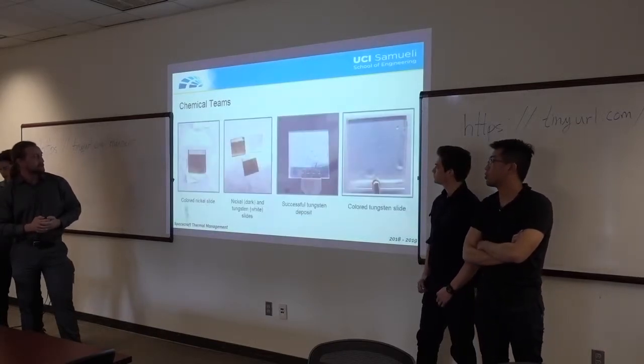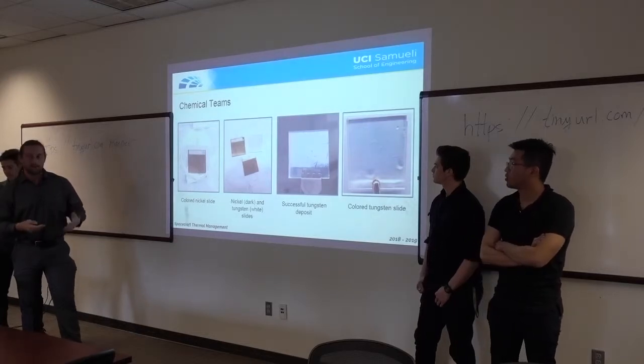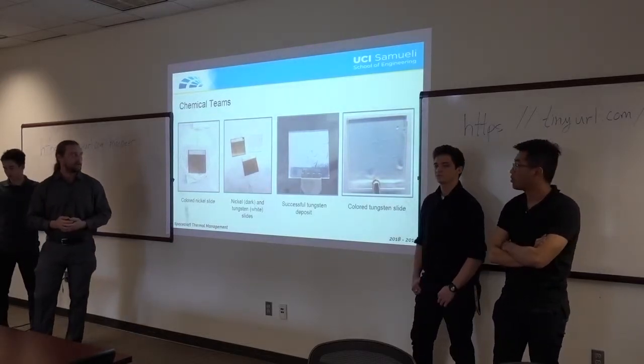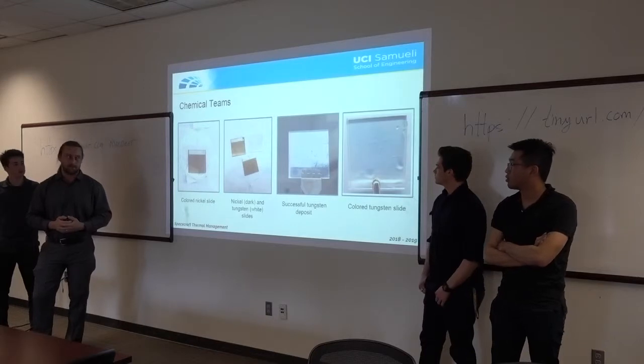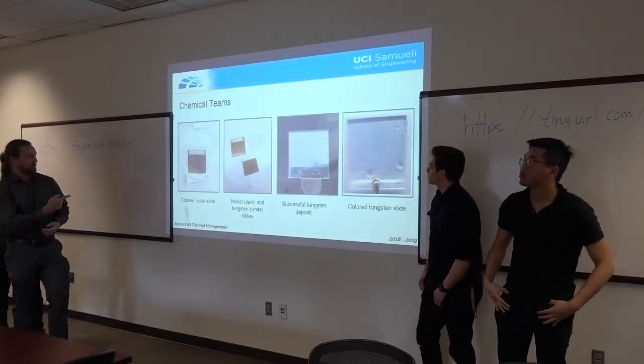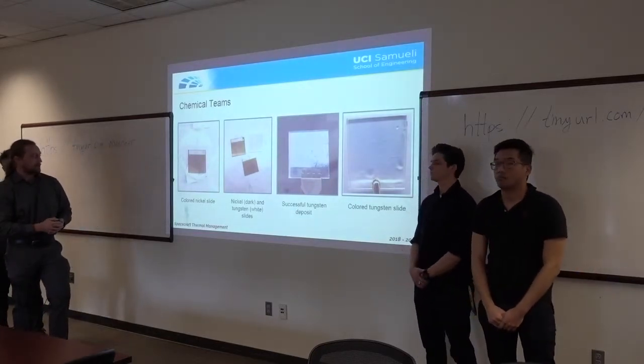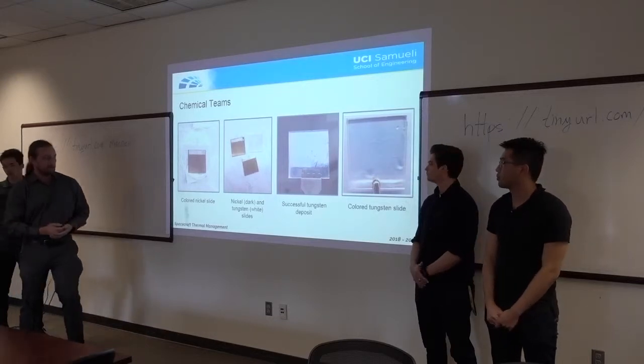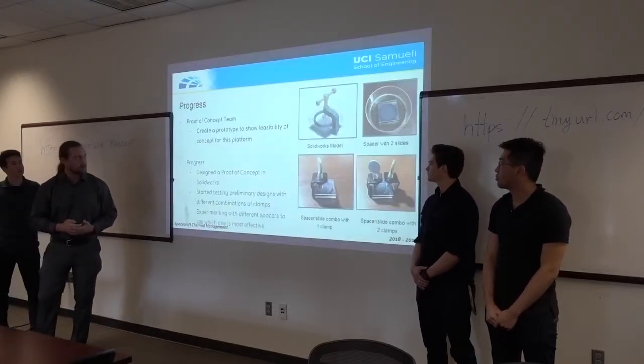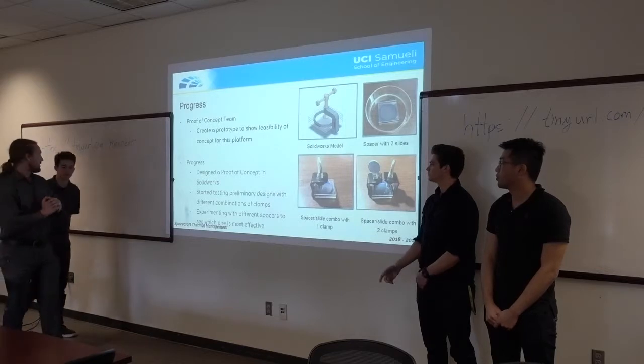And here's some more pictures. During the composition of our mixtures, we achieved varying degrees of deposition. So you can see that some of them are darker than others. We got nickel on the left and tungsten on the right. And with that, I'll pass it off to Scott.